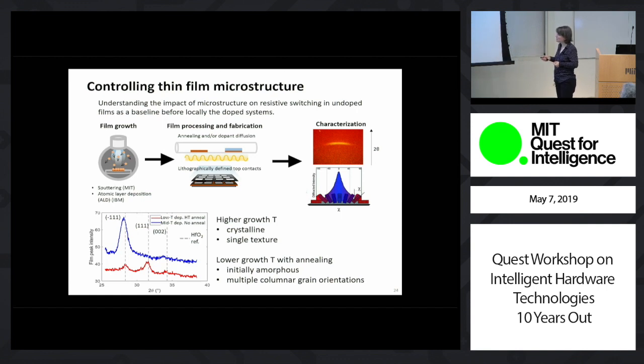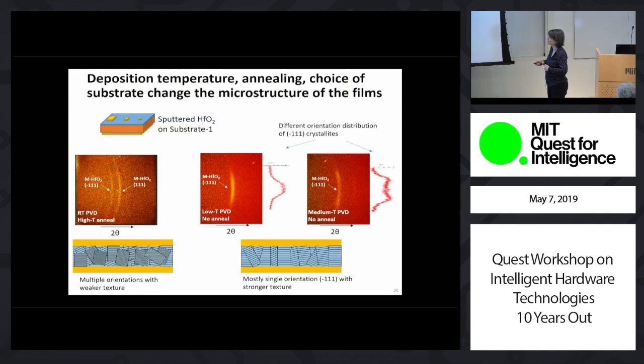Okay? So in summary, we could obtain more textured, more single texture films by higher growth temperature conditions. Whereas if you start with lower growth temperatures and then try to anneal, you don't get to as good a texture as we get with relatively high growth temperatures. Okay? So I'll just show one example here for that texture control, and I will refer you for the results on this to Kevin May, my postdoc's poster outside.